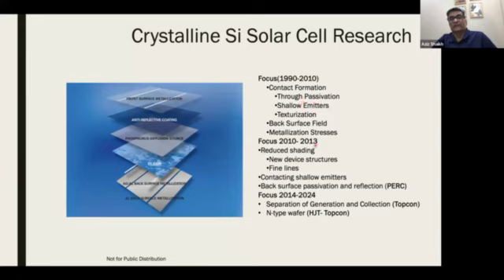Then came 2010 to 2013. So the focus was, these lines here are the areas where the light cannot penetrate through. So you lose about 7% to shading. Now that has been reduced to 4.5. So all the lines have become narrow and tall. The fine line contacting of the shallow emitter continued. And then the back surface field was replaced by back surface passivation plus back surface field. And that is called PERC technology. So that came into play.